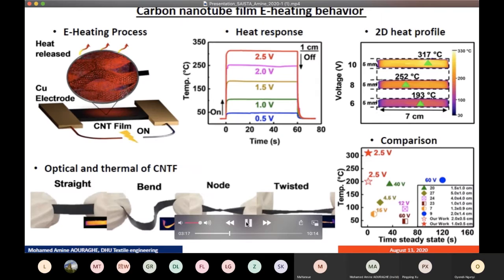In addition to being strong and lightweight, the produced CNT could be used as e-heating material. The carbon nanotube film is able to convert electrical energy into heat as shown in the figure. We attached the standard CNT film to copper wires and studied its e-heating performance. The CNT film can generate heat even after several deformations such as bending, knotting, and twisting, and can reach its steady state temperature almost instantly at the moment we input the power. We reach high temperature systematically.